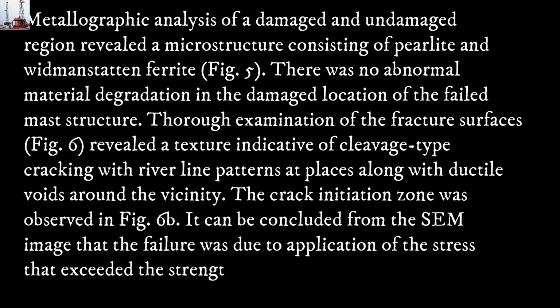Metallographic analysis of the damaged and undamaged region revealed a microstructure consisting of pearlite and Widmanstätten ferrite, Fig. 5. There was no abnormal material degradation in the damaged location of the failed mast structure.